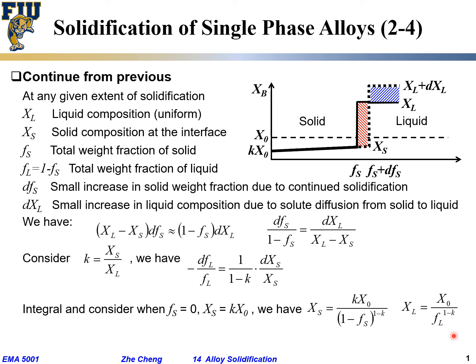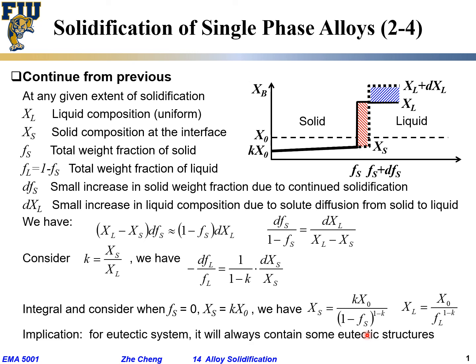If we have such a system, if we make certain assumptions, no diffusion in solid, uniform within liquid, linear relationship between the phase boundary, then we can mathematically, analytically derive a simple relationship that describes our local composition right at the interface, depending on how much solidification has happened. Okay? Here, of course, we don't go into further detail of the mathematics, but you can do it yourself. Going from here to here should be simple. And from here, integration should also be simple. Okay?